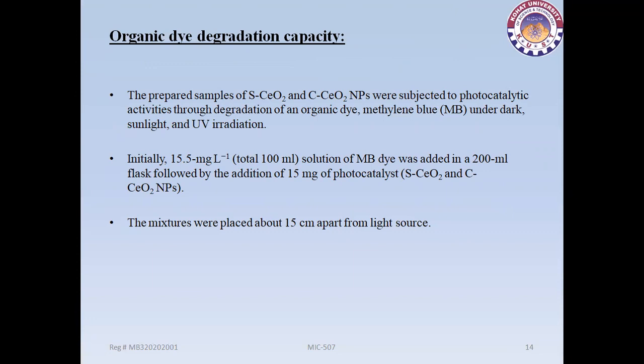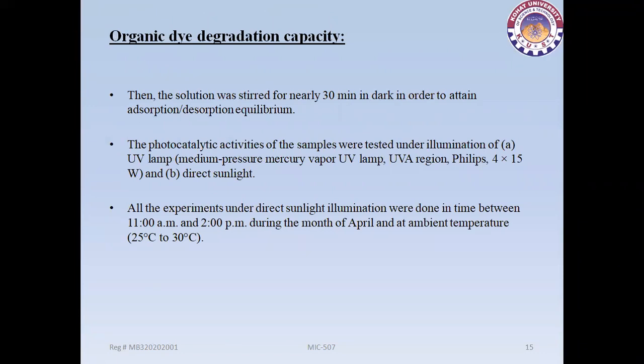Initially, a total of 100 ml solution of methylene blue dye at 15.5 milligram per liter was added in a 200 ml flask, followed by the addition of 15 mg of photocatalysts of spherical and cubical cerium oxide nanoparticles. The mixture was placed about 15 centimeters apart from the light source. Then the solution was stirred for nearly 30 minutes in the dark in order to attain desorption equilibrium. The photocatalytic activities of the samples were tested under illumination of a UV lamp, medium pressure mercury vapor,